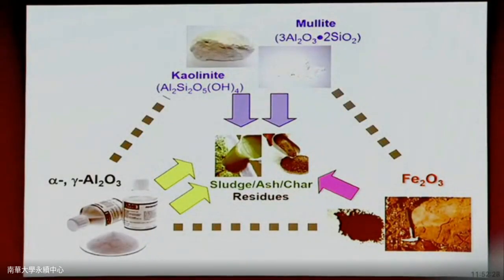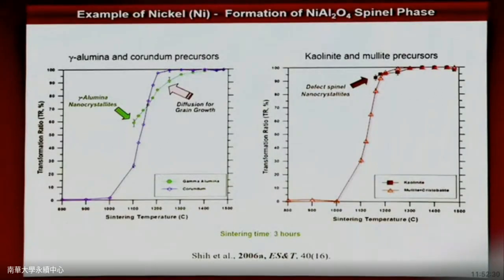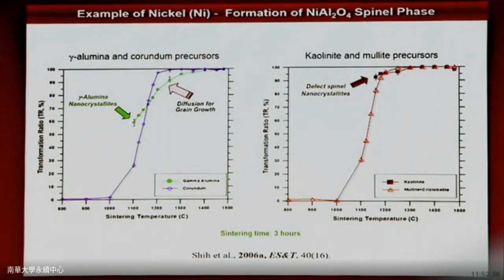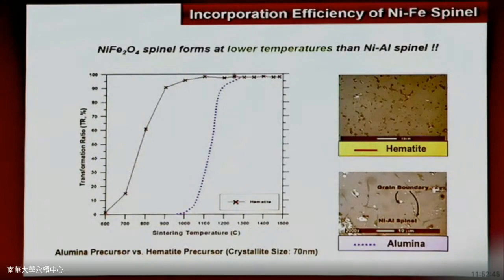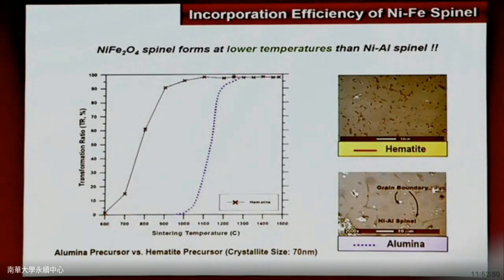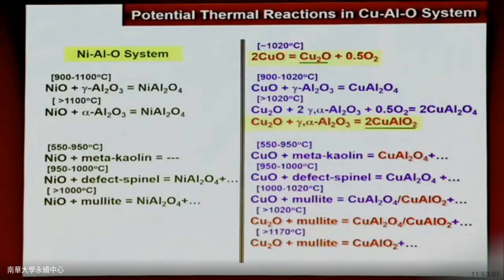So we start to look at all these heavy metals, how they actually incorporate into different kinds of matrices in the geomaterial, and we try to see, for example, this is a nickel leaching capability being hosted by different types of mineral phase, and we find out some of them are better, some of them not so good. But the good thing is that, yes, if you have a good mineral phase there to stabilize your heavy metal, then even if your heavy metal is incorporated in your residues, it actually doesn't release into the natural system. It doesn't actually release into your fertilizer. Well, it's there, but it's not soluble, not absorbed by the plant. Nothing wrong with that. So that is an important skill that we'd like to look into.